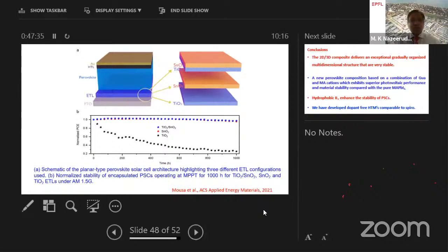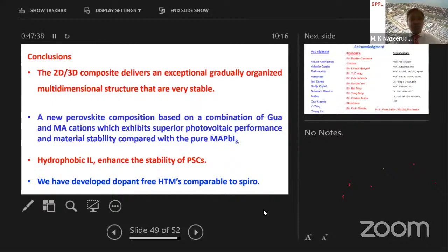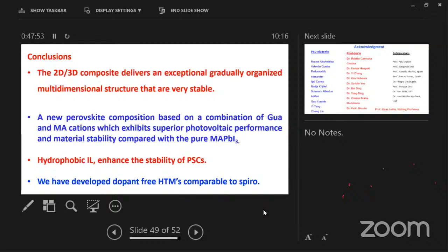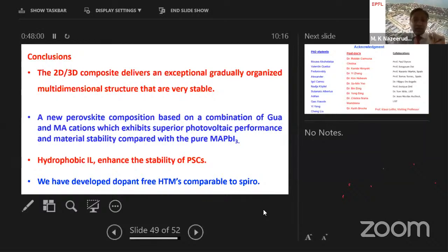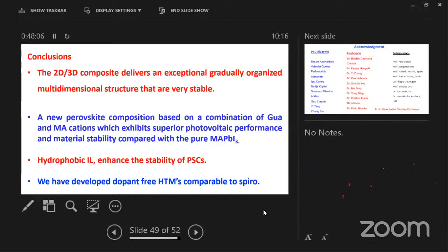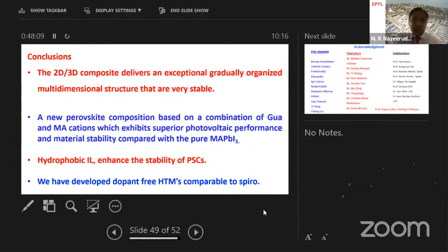Next slide. In my presentation, what I tried to show you is how to increase the stability by combining two-dimensional perovskite and three-dimensional perovskite. That's interface engineering that reduces the recombination and increases the stability. At the same time, I have shown you the composition engineering of guanidinium and different organic cations that enhance stability, and the ionic liquids containing hydrophobic groups also enhance stability, and the new hole transport materials showed enhanced power conversion efficiency.